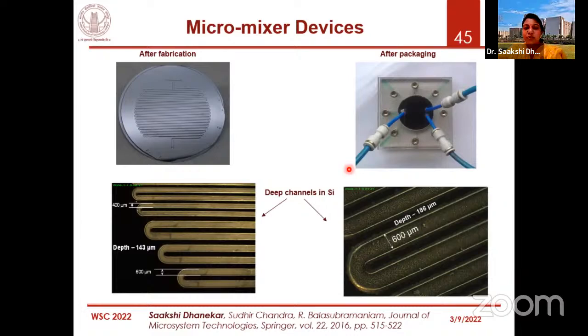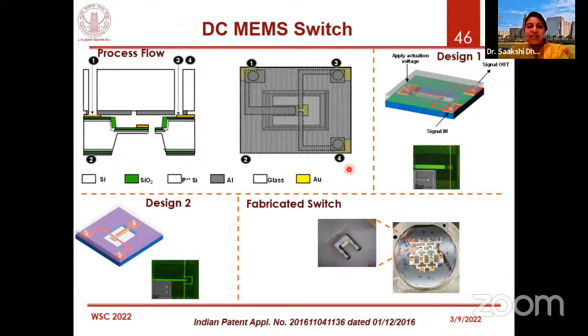So the channels were sealed using anodic bonding, where we had this glass wafer at high temperature and high voltage that would bond hermetically with the silicon wafer. So this gave us great results, and we could try out a lot of things with our silicon wafer, because when the facilities are available, you can do multiple things at the same time. The other thing that we had worked on is the DC MEMS switch.